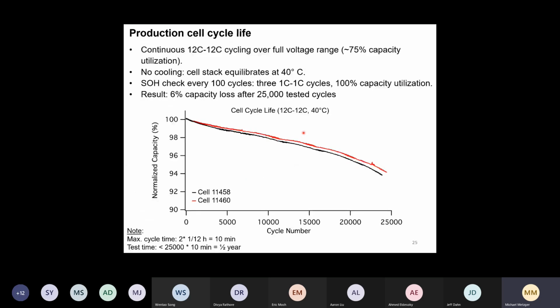And then how about cycle life of this production cell? So one positive aspect of these batteries with a really high rate capability is you can get a lot of cycles in a fairly short time. So they cycle their battery at 12 C, charge and discharge, over the full voltage range, which allows them to access 75% of the capacity. They don't need any cooling in their cell. I mean, at these high rates where you have quite a high current flow, the cell heats up to about 40 degrees C, but not more.